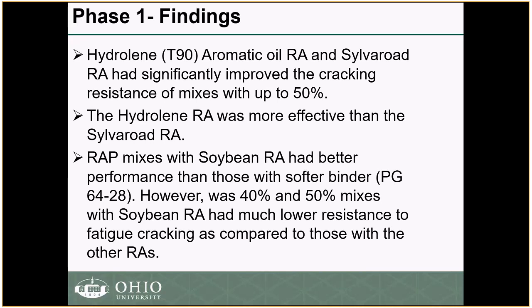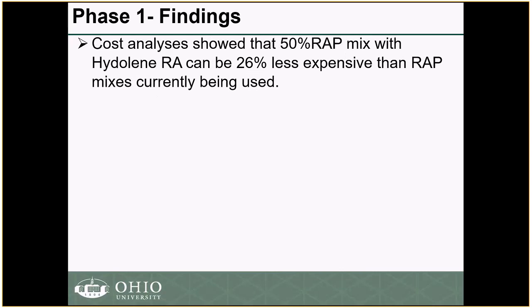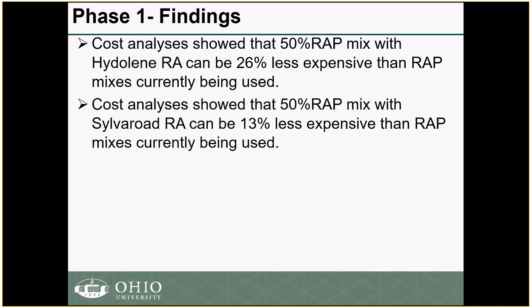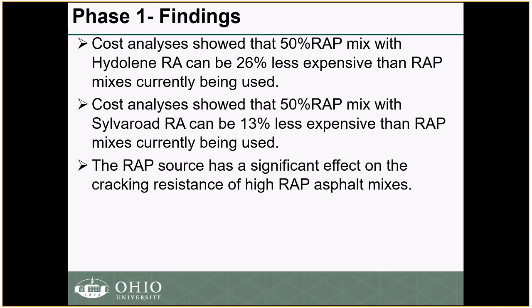So what we have noticed is that the soybean is really resulting in a softening effect, and therefore it did not significantly improve the fatigue cracking resistance of RAP mixtures when using more than 30% RAP. In terms of cost analysis, if we are comparing to the 20% RAP, the one that is currently used, using Hydrolene and 50% RAP can result in more than 26% reduction, as compared to the Sylvaroad, which will result in this case in 13%.